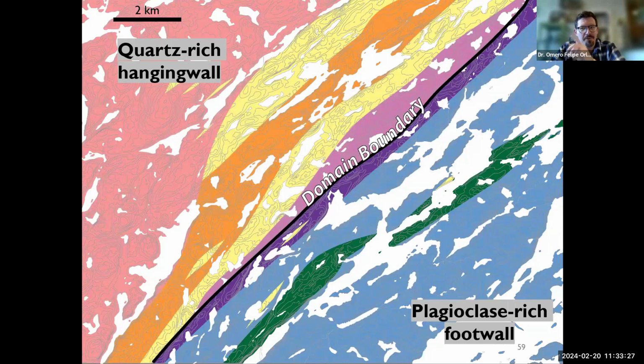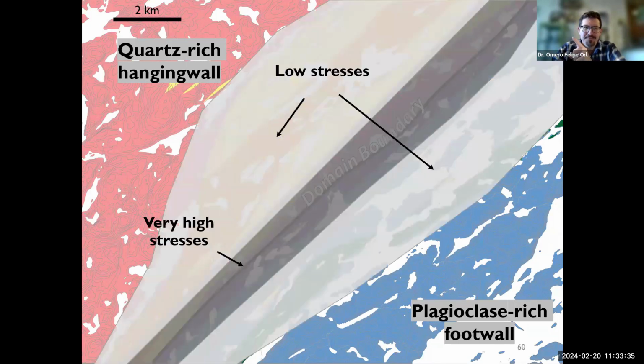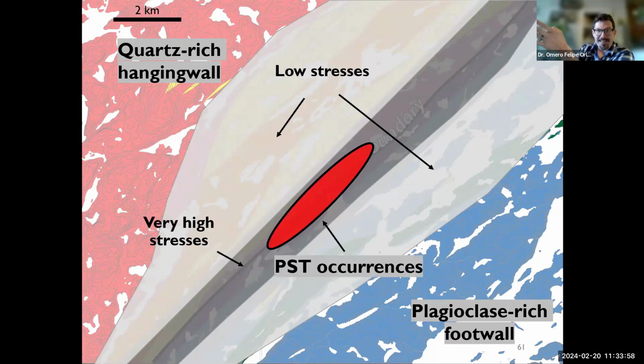And so now we're going to get back to the real important part about all these lithologies, right? Which is that one is quartz dominated and one is plagioclase dominated. And that ends up mattering a lot. So we're going to summarize our grain size study with: all right, low stresses-ish out in the mylonitic parts of this shear zone, but then really high stresses right in the core, which also corresponds to this domain boundary where the lithologies do a major flip from being really plagioclase rich to being really quartz rich. And on top of all that, we have our smoking gun, which is this super weird mechanical behavior happening right where these stresses get super high.